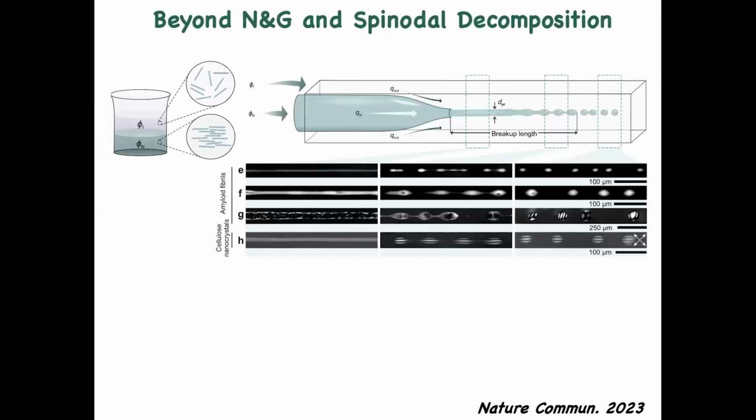And now what you need to do is simply take the nematic phase, and you re-extrude the nematic phase into the isotropic phase. And what you form, you have to do it fast enough because you break the jet with the Rayleigh-Plateau instability. But if you do that fast enough, you're able to generate droplets again. And the beauty is that depending on the flow, you can generate droplets again of different size, and again you see different sizes correspond to different symmetries. This is the nanocellulose, you can form directly uniaxial or bipolar tactoids.